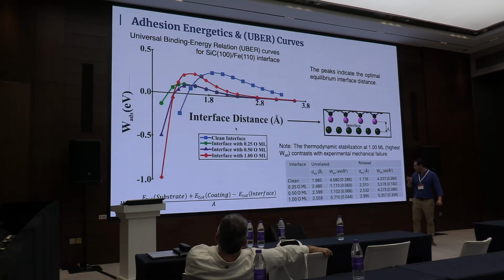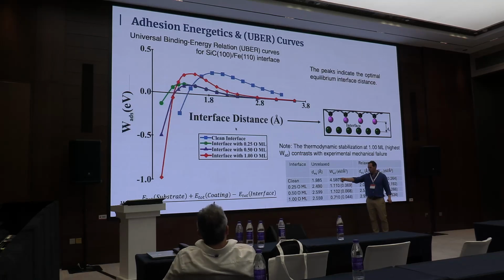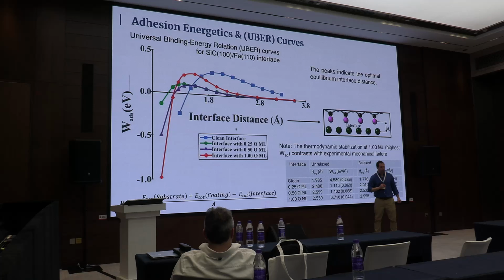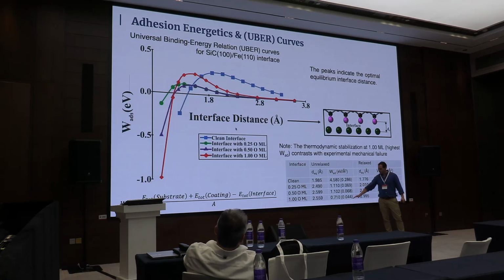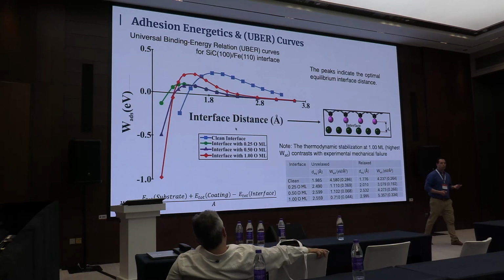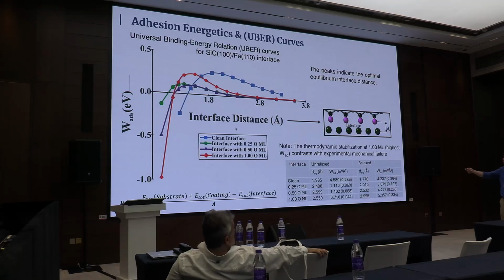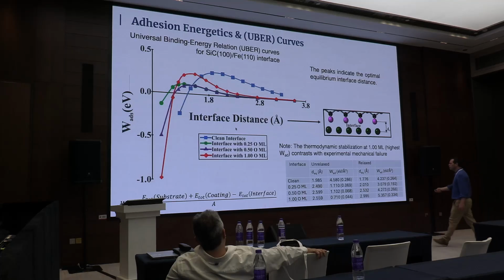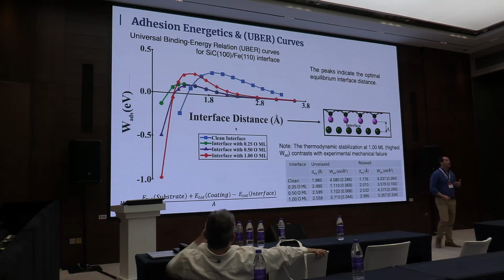But when we increase the concentration of oxygen, this amount decreases. That is okay, it is what we need to find. Why? Because if this amount is higher, it means more adhesion force. If not, it's lower. So it's how much it costs to separate the surfaces. This is the measurement that this energy gives us. Okay, we are in good agreement with the experiment, but no. Why not? Because this is an unrelaxed system.